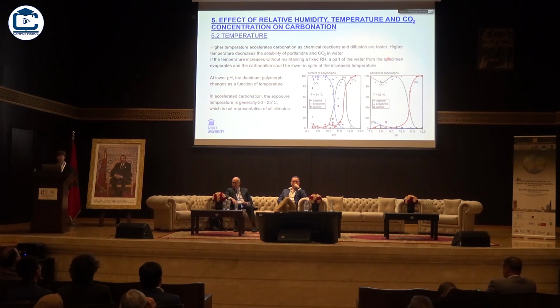Also, temperature has other effects. It accelerates chemical reactions, also carbonation, but it also dries out your structure. And then, if the relative humidity is dropping below this critical value, the carbonation rate will decrease. Furthermore, the polymorphs that are formed may be different. At high pH, you always have calcite, but at low temperature versus high temperature, you might have different proportions of the vaterite and the aragonite.